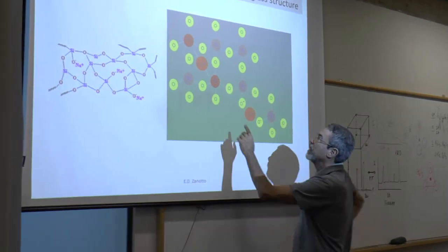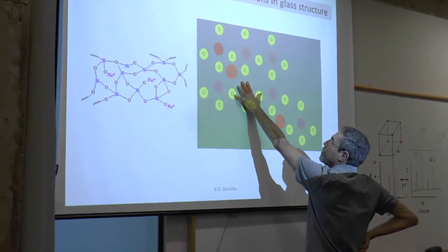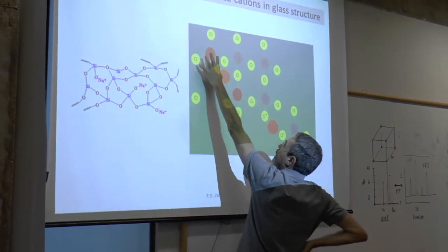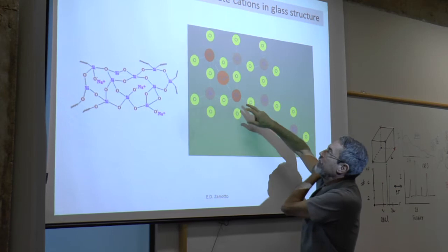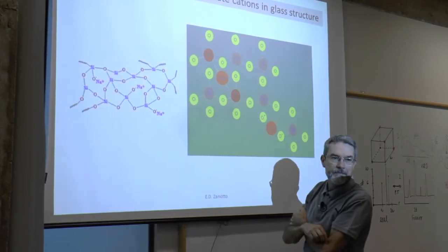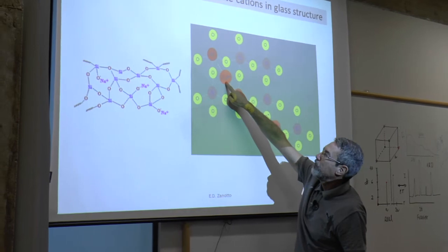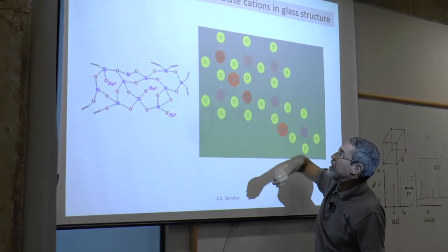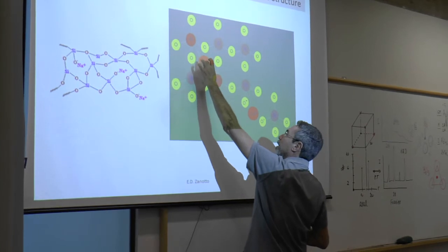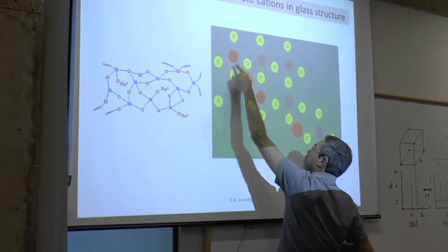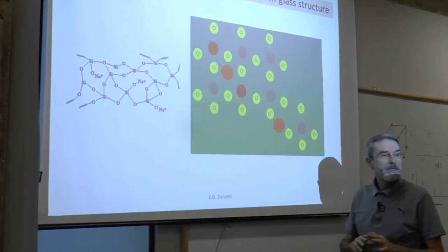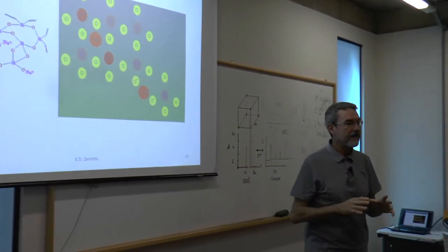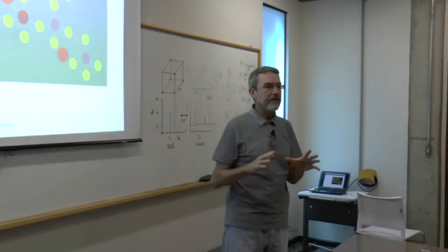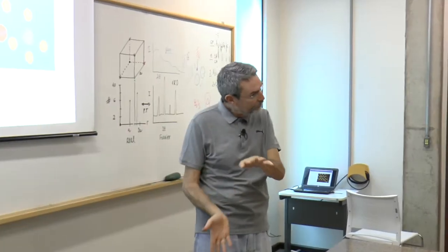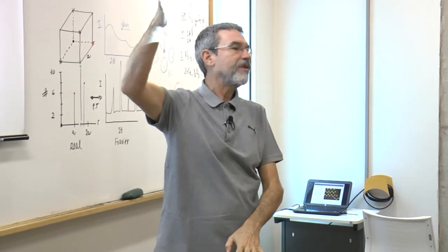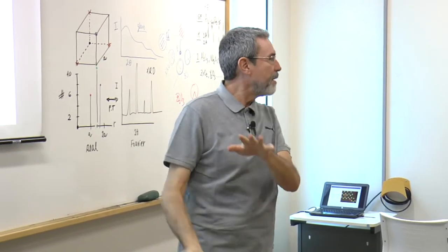So now look at this glass here, aluminum coordination 4, aluminum coordination 4. So it has recovered 2 non-bridging oxygens that were formed by calcium in this particular glass. So, well, calcium is still there, somewhere in a complex type of linking, but the non-bridging oxygens have disappeared. So this is like a healing effect. It's a healing effect of glass. So the viscosity increases again. And the thermal expansion coefficient decreases, and the chemical durability increases.